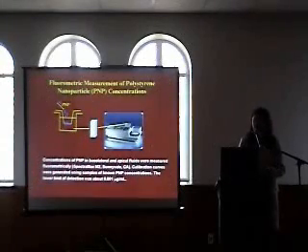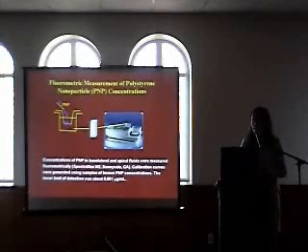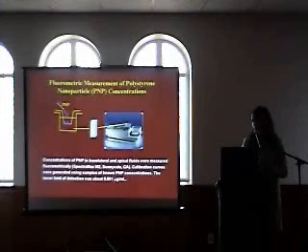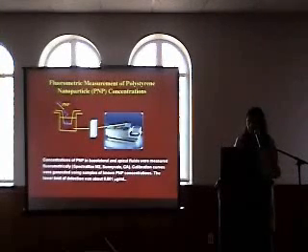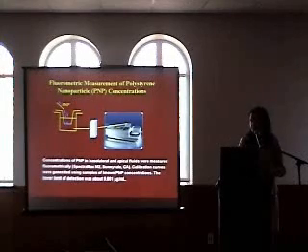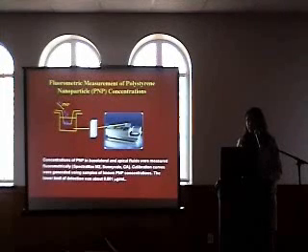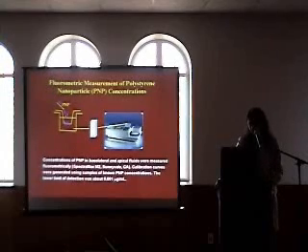This slide just really quickly shows the method we use to look at the effects of nanoparticles on the lung. We were able to get fluorescence-labeled polystyrene nanoparticles from Molecular Probes. They come in two different sizes and with different surface characteristics. We apically expose these cell monolayers to these nanoparticles, and by measuring the accumulation of these nanoparticles in the basolateral side, we could calculate the transport rates of these particles.